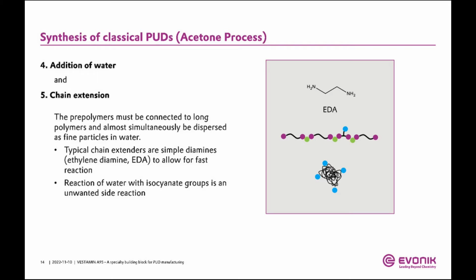But when you go lower to this scribble, you should just envision, or picture, that if you have then finally your particle in water, your organic, your hydrophobic parts will stick to the inside, and the hydrophilic groups will stick to the outside, and they will then cause this stability of the particle in the water, so that by these hydrophilic groups sticking to the outside, you kind of physically hide the organic hydrophobic groups from the water.